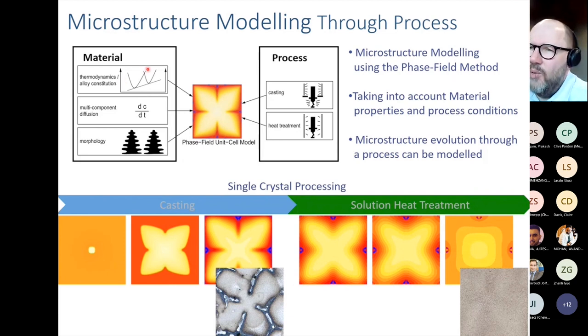So we incorporate the Gibbs energies and minimization of Gibbs energy in order to inform our phase field model: how the alloying elements will partition between the different phases, creating the segregation we've already seen, how we get driving forces in order to describe the evolution of morphology, and also how we nucleate new phases and then have secondary phases forming. That's describing the material side.